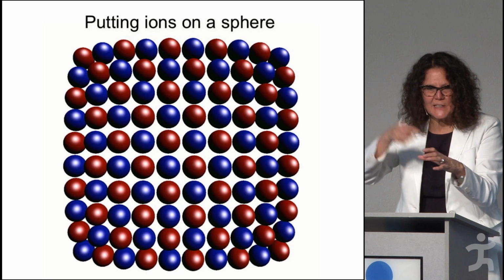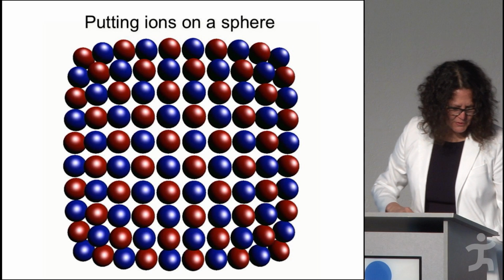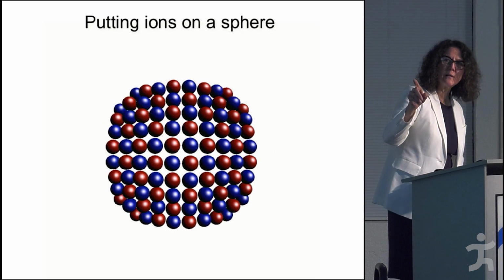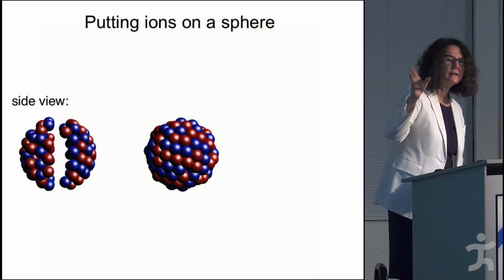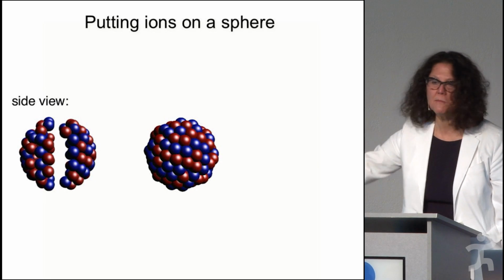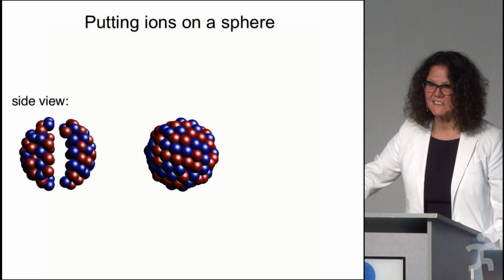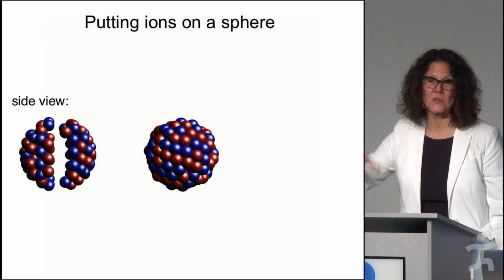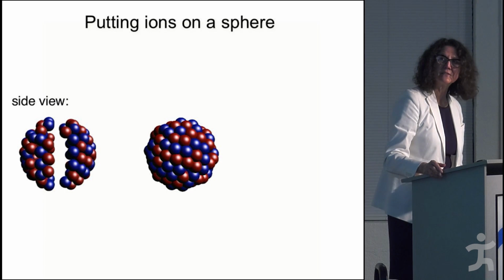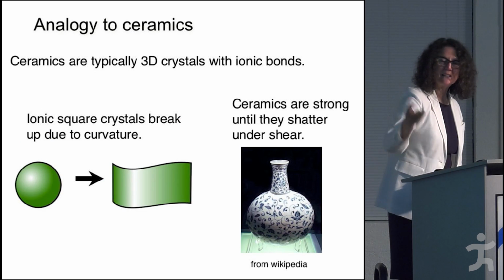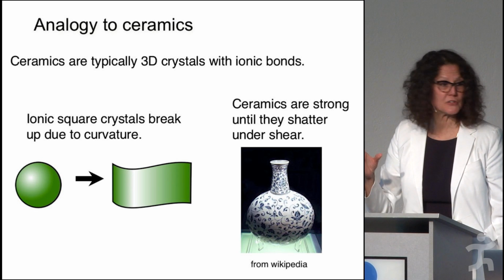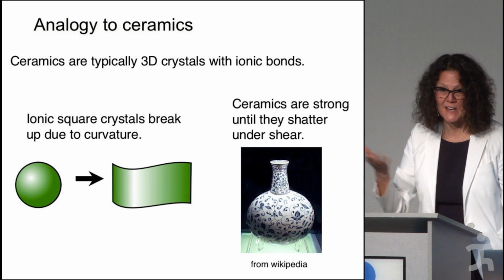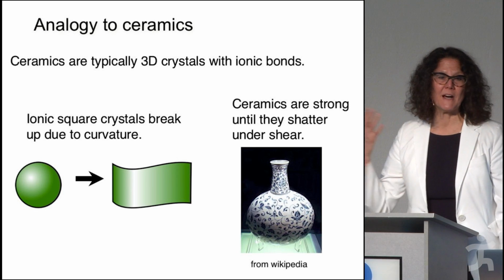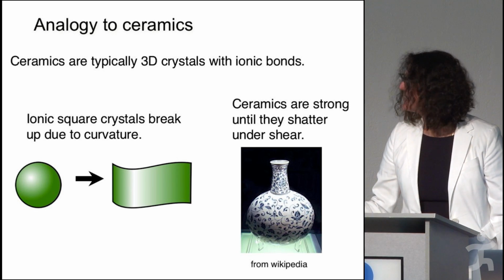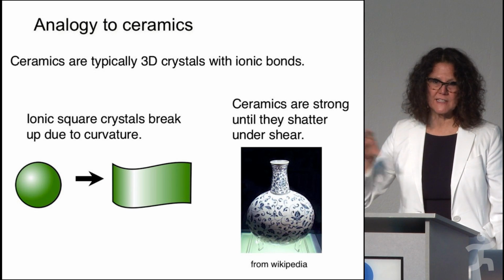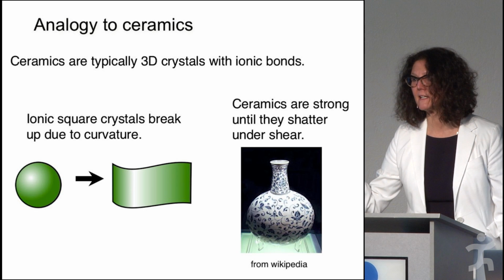And then you start deleting the water, so it gets more and more concentrated. If you do that, you go smaller, smaller, smaller, and at some point, it has to form a hexagonal. So it no longer can support a square lattice. So when it's densely packed, these structures do not support the hexagonal structure in the spherical shape. So you might think that's why ceramics, which are ionic structures, plus minus, you don't find many of them that are plastic; they crack very easily and so on. The reason from a materials point of view is because the theorem I told you about the defects also has to obey here. But the defects are different.